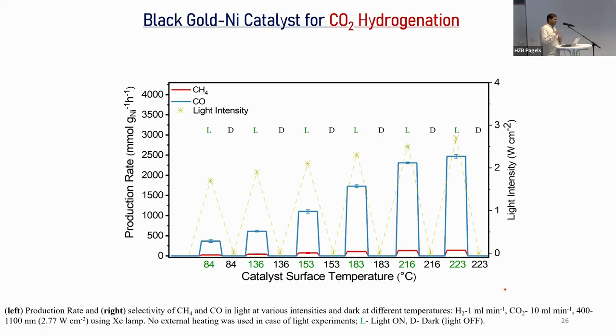But then the opposite argument is that it may not be the real temperature of your surface. The surface temperature could be really high, which we are not able to measure. And maybe because of that, the reaction is happening, right? And it's not hot electron mediated, but because of localized thermal heating. Now, how do I answer this question? The best way we can do as experimentalists is insert the thermocouple and use our camera to get the temperature. If you don't believe in those temperatures, how do we find out the temperature of these surfaces?